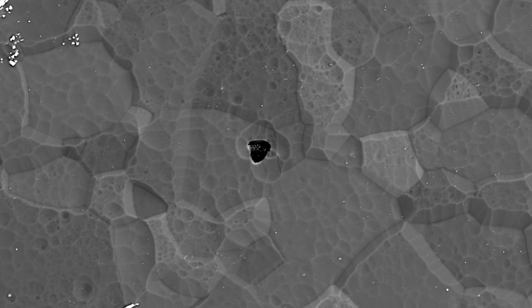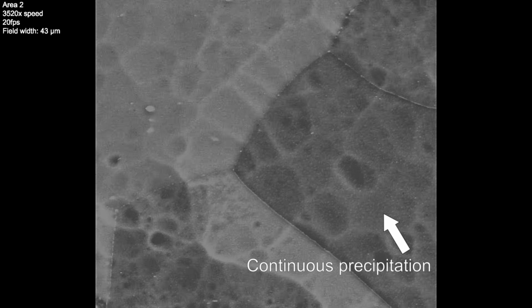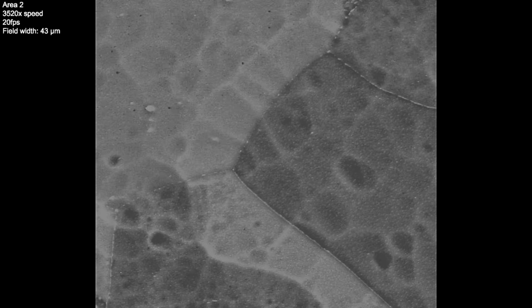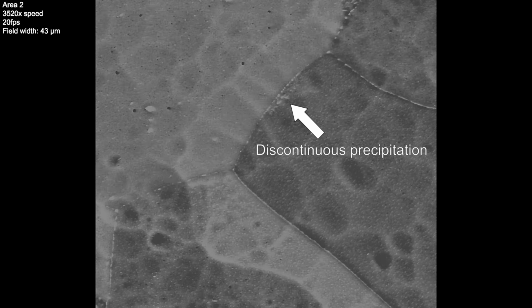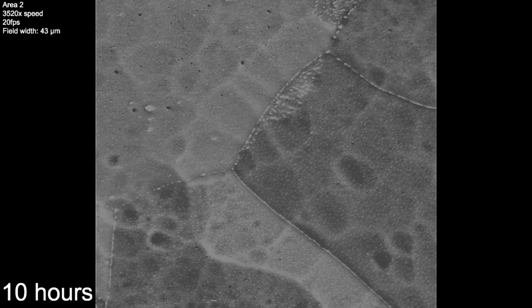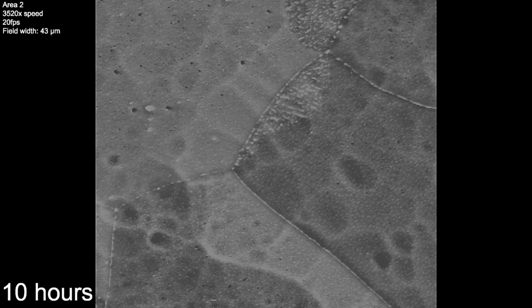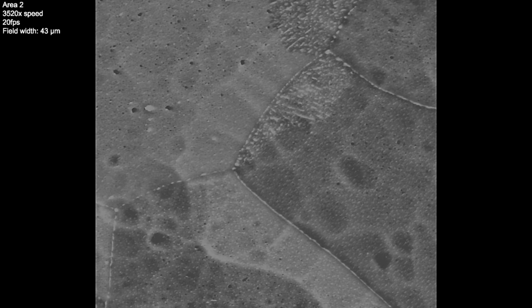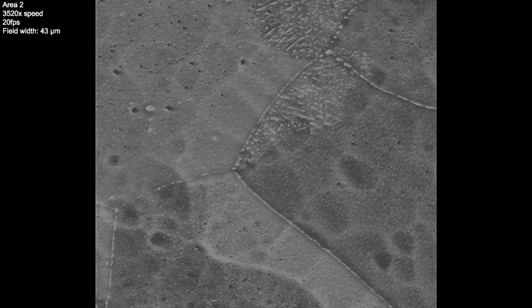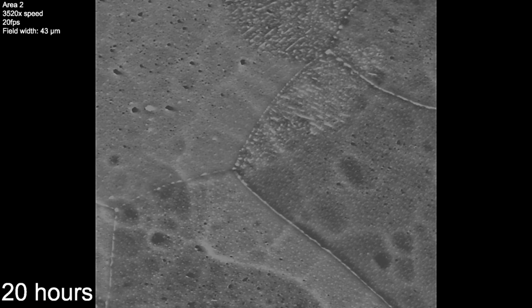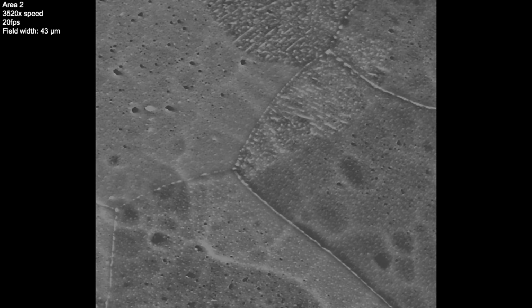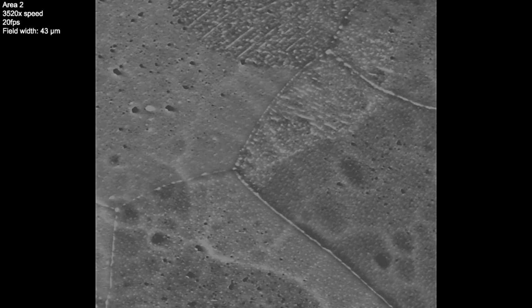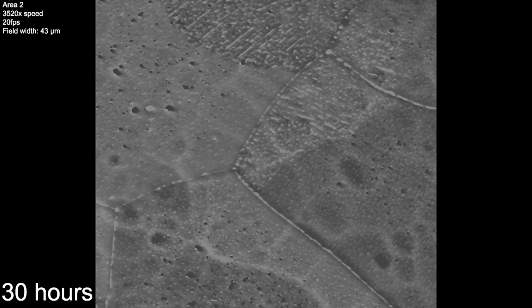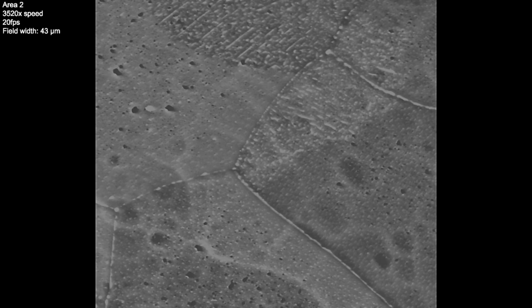I've zoomed in on 2 areas out of the full high-resolution video we captured. First, you can just about see the continuous precipitation form within the grains. These are the tiny white dots. Then, the discontinuous precipitation appears at the grain boundaries and storms across the grain, eating up the continuous precipitation as it goes. Clearly our theory was wrong. They are not in competition. It just seems that way when you look at this sort of microstructure after the heating cycle at room temperature. You can see that as the discontinuous precipitation front invades the grain, it coarsens and joins up the continuous precipitates to create large, useless particles that we so hate.